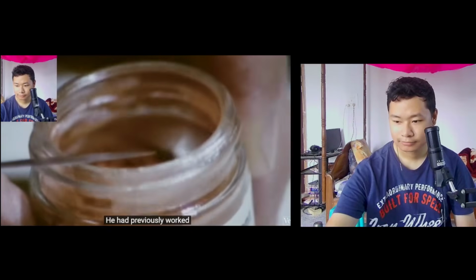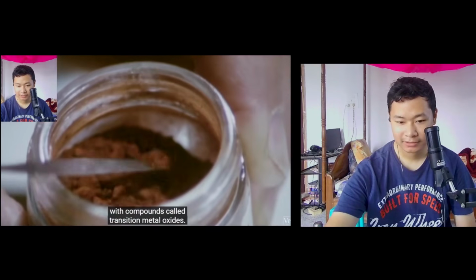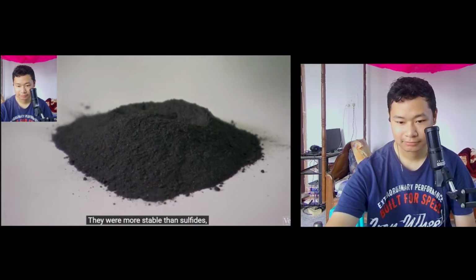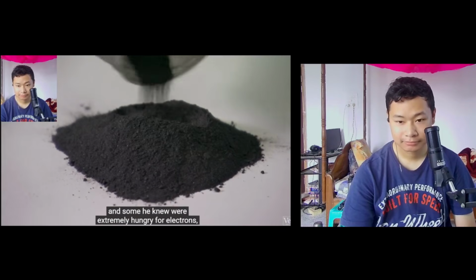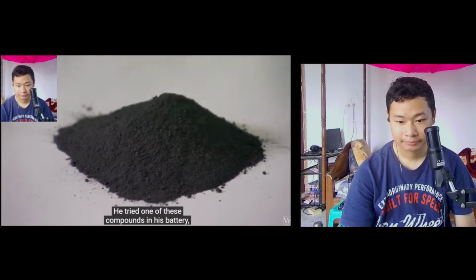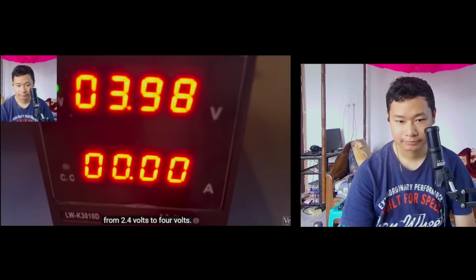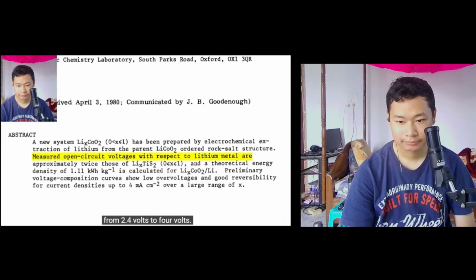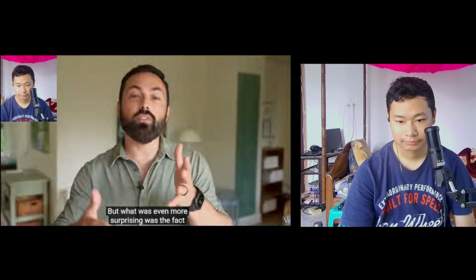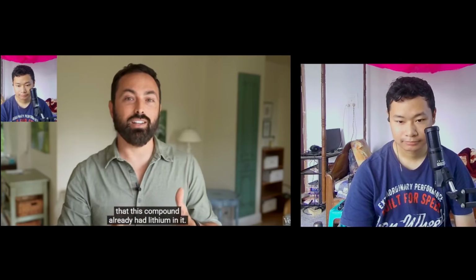He had previously worked with compounds called metal oxides. They were more stable than sulfides, and some, he knew, were extremely hungry for electrons, perfect for a cathode. He tried one of these compounds in his battery, and the voltage immediately spiked from 2.4 volts to 4 volts. This jump was incredible. But what was even more surprising was the fact that this compound already had lithium in it. The material was lithium cobalt oxide.